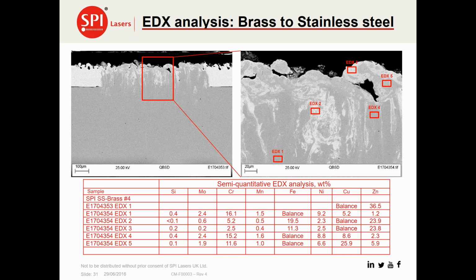Here's a final example of brass, for example, to stainless steel, showing the same thing. You can see here brass on top, stainless steel on the bottom. Again, although we're seeing mixing, effectively stirring of molten metal, which is then solidifying, you're not actually seeing any alloys forming within the joint.